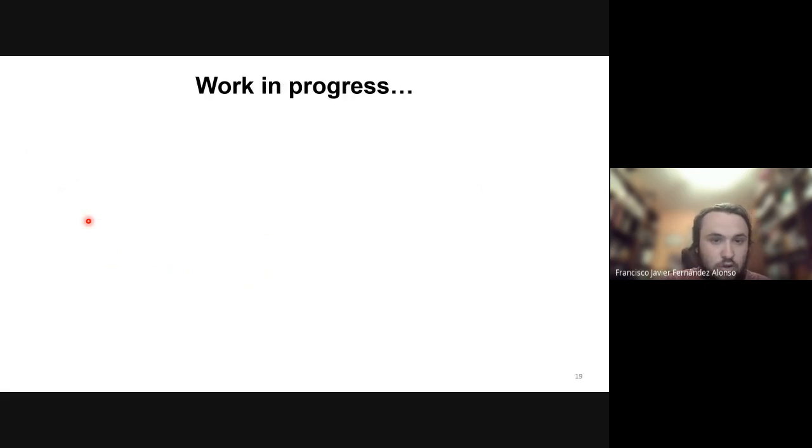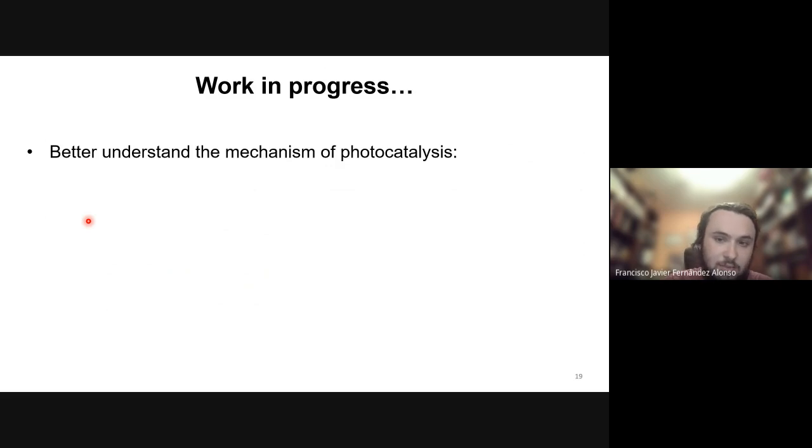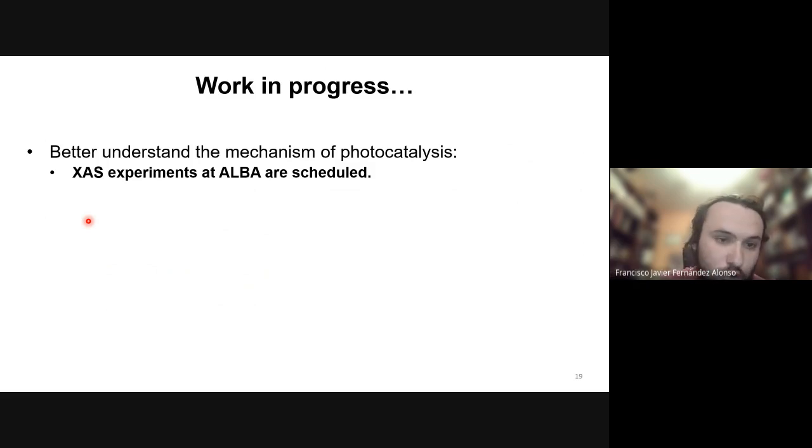So we have some work in progress. We would like to better understand the mechanism of photocatalysis. For that, we want to perform X-ray absorption spectroscopy experiments and XPS experiments. Since XPS is a much more surface sensitive technique, we can see if these defects are on the surface. We expect so, but by also performing X-ray absorption spectroscopy, we can see if these defects are only on the surface or if they are also in the bulk, since X-ray absorption spectroscopy is a more bulk sensitive technique.